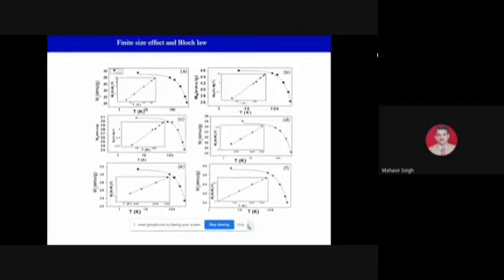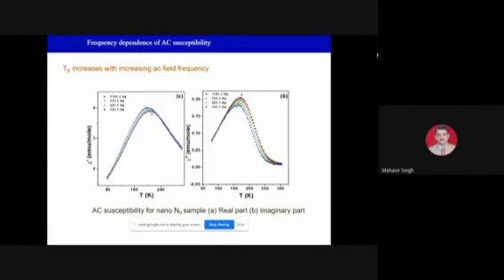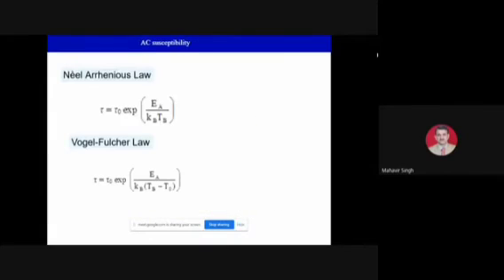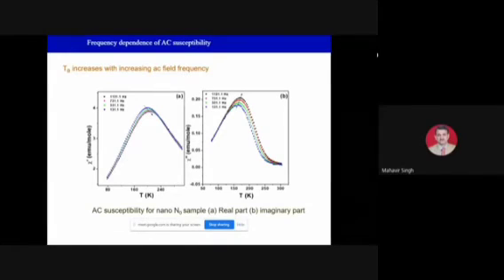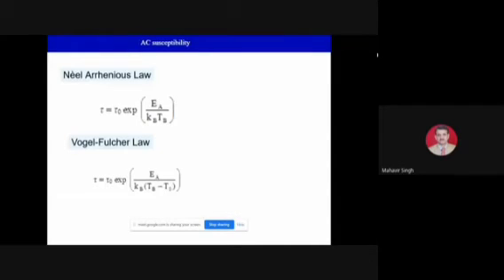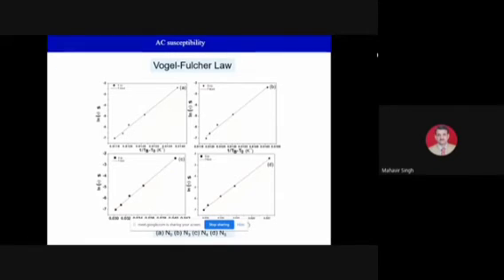Next, please. So again, all these. Next, please. So again, this is basically the model we apply. So we tried the Vogel law, then the Neel law. So we try to fit it. Next, please. So this is the Vogel law, and we found that in our observation, it was the Vogel law which was very well helpful. That is the spin glass transition. Next, please.